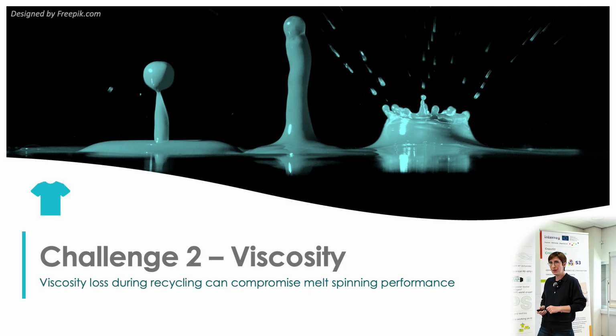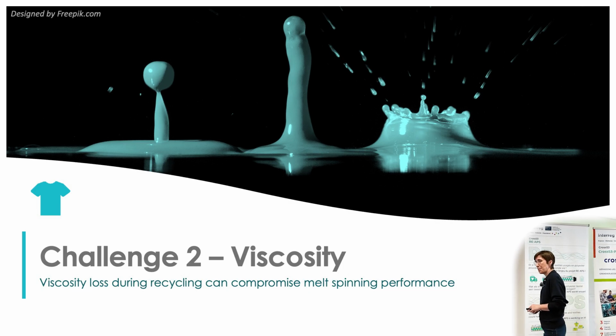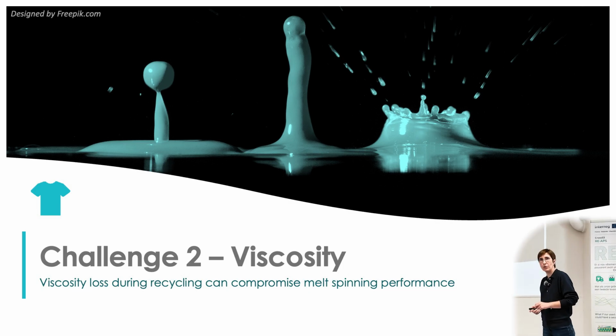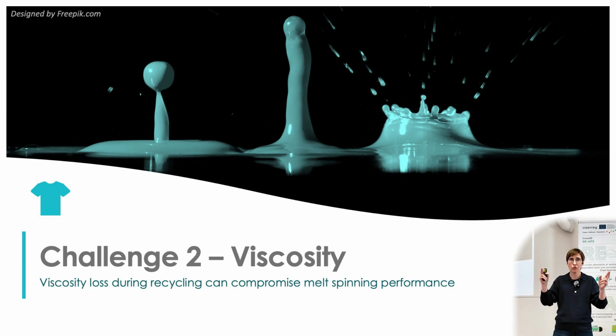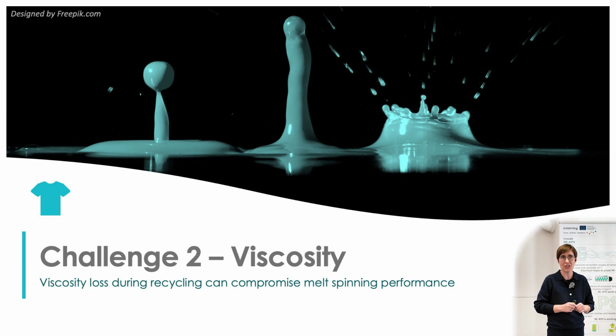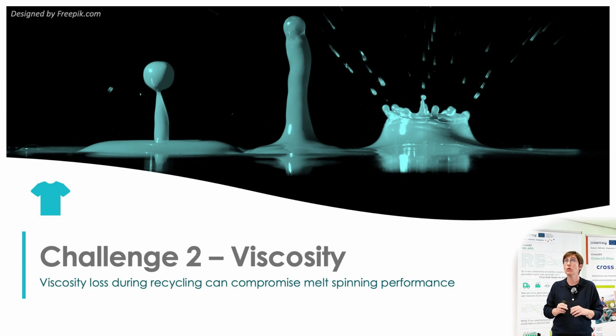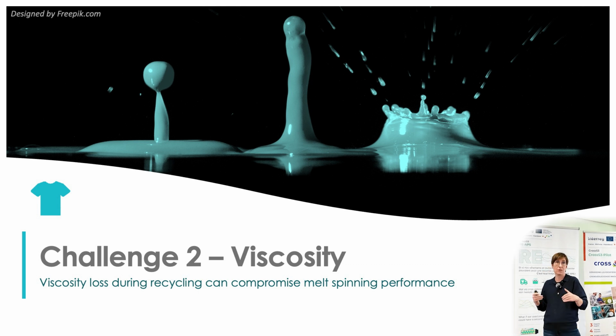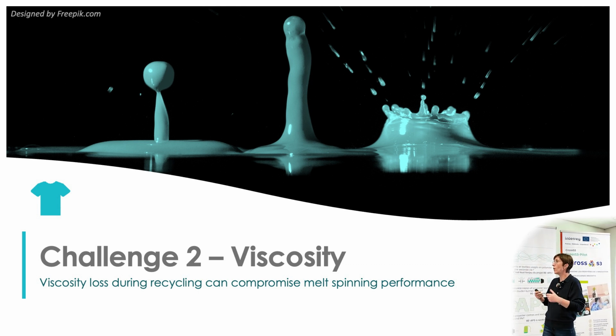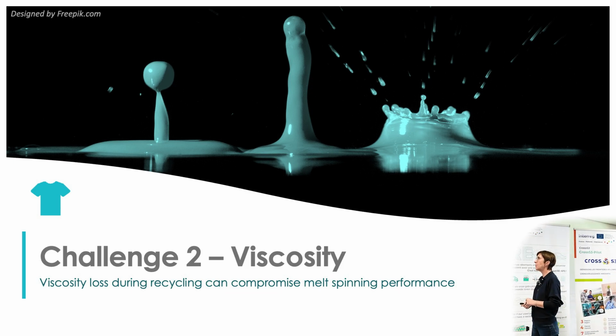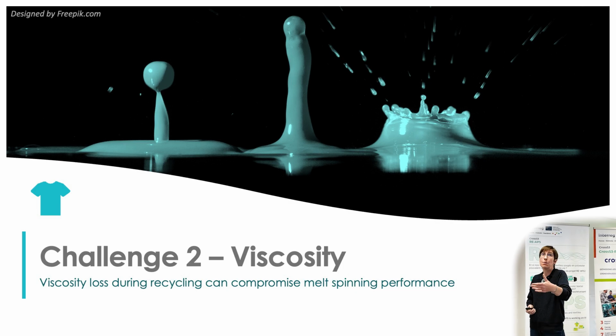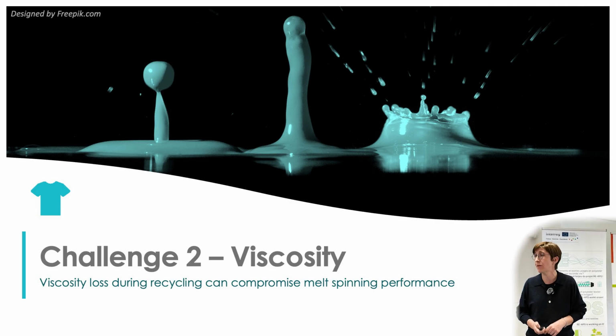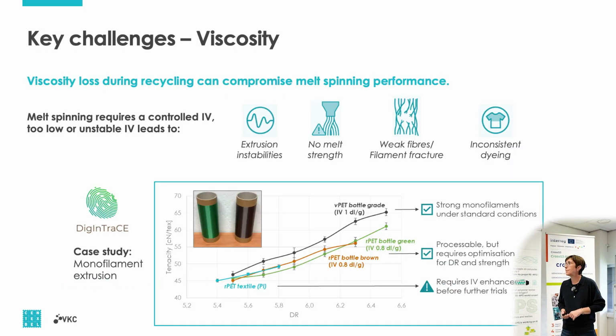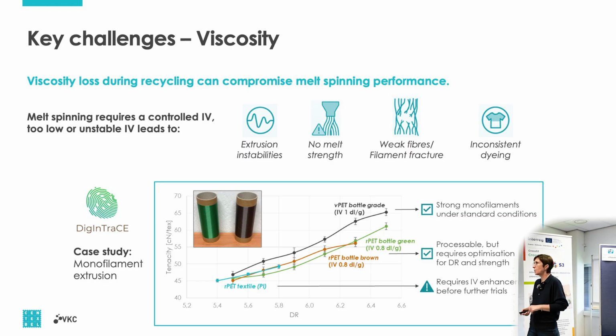We are working with polymers, we're working with polyesters. Polyester is quite sensitive to hydrolysis. It means that you cut your polymer chain into smaller pieces. When you cut the polymer chain, you lose your mechanical strength. So this is something you want to avoid, and you want to keep your polymer chains as long as possible during your reprocessing, to make sure you're again able, for instance, to make a high tenacity polyester fiber. What can you do there? Because what will happen if you're cutting your polymer chain?